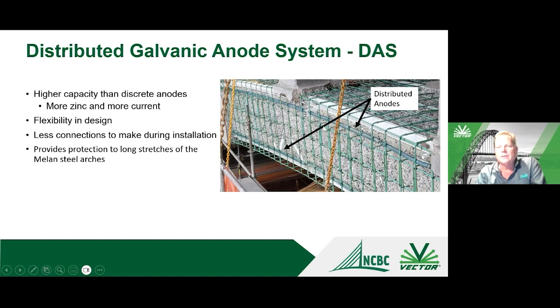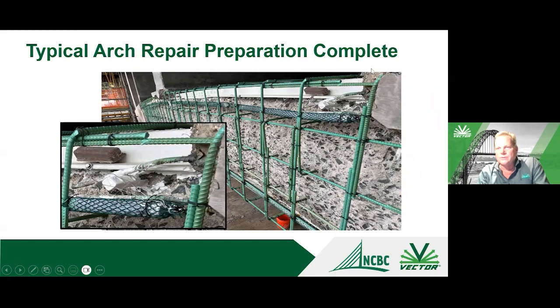And to protect the underlying steel here, you see the distributed anodes placed along the structural steel frame at the top and the bottom. And then at the edges where you have the existing sound concrete that's going to be adjacent to the new concrete, that's where we also use some type 1 anodes. You see them connected to a drill and tapped self-tapping screw into the structural steel frame, as well as the distributed anodes to the same connection. And so that's a very, like I said, very comprehensive mix of repair, strengthening and application of corrosion protection to the repair.